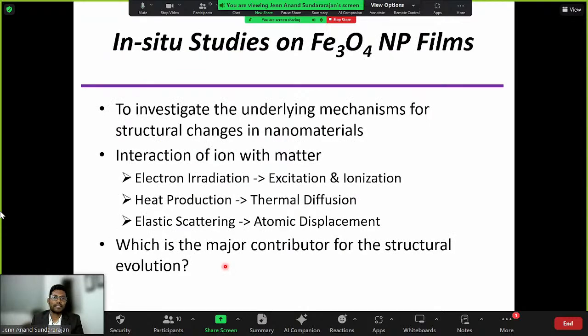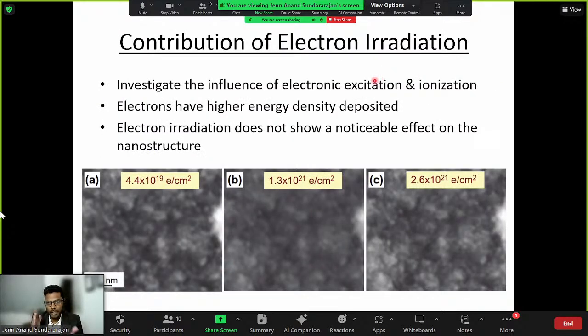Let's take a close look to see, hey, I irradiated the sample, I know with electron radiation there could be some ionization that could happen, right? Because we are talking of electrons. Could that have played a role? That's what we find out here. And as you can see, with any amount of electron radiation, the particle size and the structure did not change. This is an in situ study. So electron radiation, although it has some contribution to heat, did not have a high contribution to the agglomeration of the particle. So we can easily eliminate electron radiation. We're going to break things down, right? Electron is not the suspect, it's excluded. Let's go to the next one.